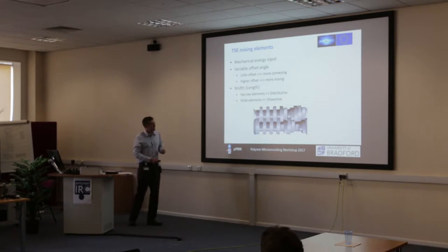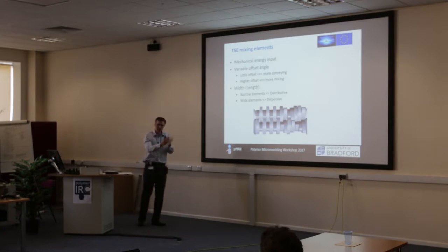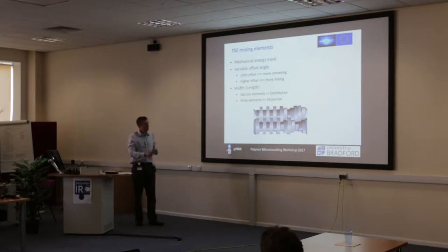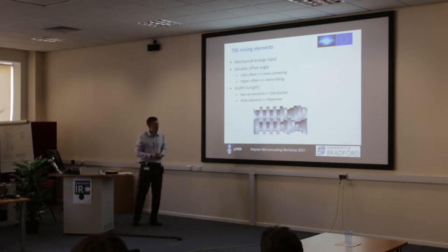And we can change the width of these angles as well. So we have very narrow width of these kneading elements. We have distributive mixing, so we realign the flow. If we have very wide paddles, we have dispersive mixing, where we form high shearing forces to break up the particles.